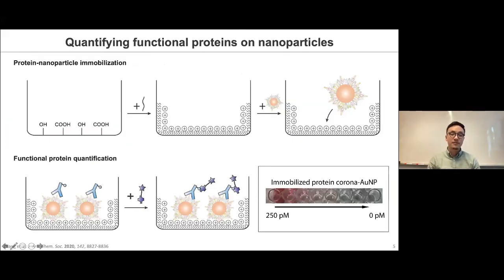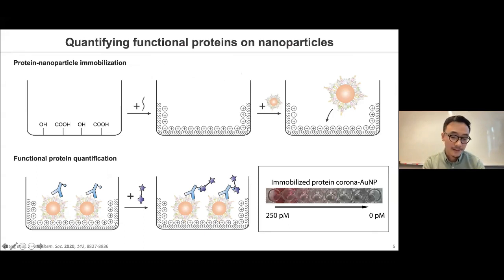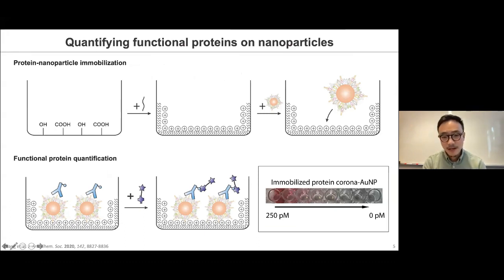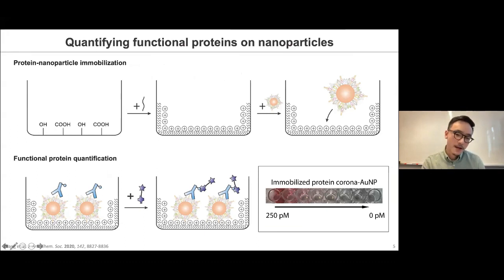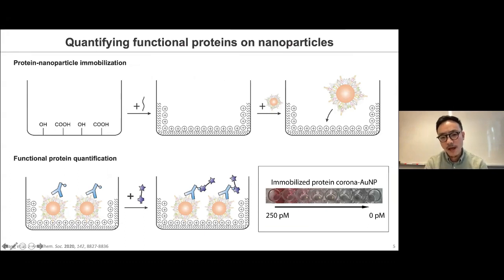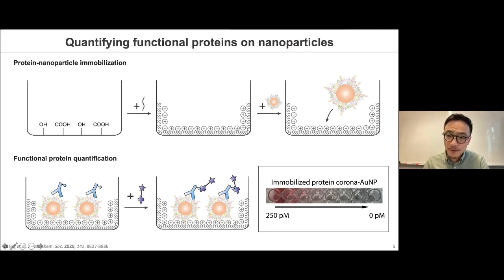We started by looking at protein functionality on nanoparticles, and we developed a slightly modified immunosorbent assay, also known as ELISA. We achieved this by first immobilizing our nanomaterials on a solid substrate — positively charged micro-well plates. These wells are positively charged by incubating with polylysines, which are positively charged at pH 7, while the proteins on the surface of particles are negatively charged at pH 7. We then use electrostatic interactions to immobilize our protein-coated particles onto the well plates, and the immobilized particles form a red color on the well.